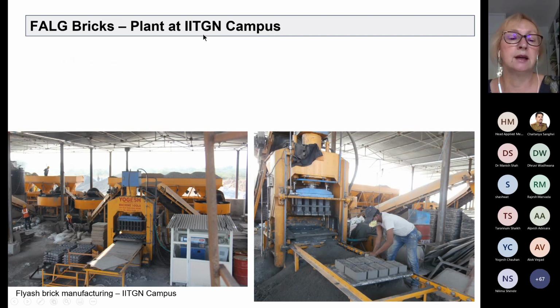When the IIT Gandhinagar campus was constructed, there was first an idea to use clay bricks for the load-bearing masonry, because practically all the residential portion of the campus is in load-bearing masonry. As we said, it's confined masonry. So there was a need for a minimum class 7.5 of clay bricks. However, it was not possible to get bricks of that class in sufficient amounts for the campus construction, and there was limited time. The construction had to be completed. Therefore, a decision was made to use fly ash bricks and to set up a plant at the campus.